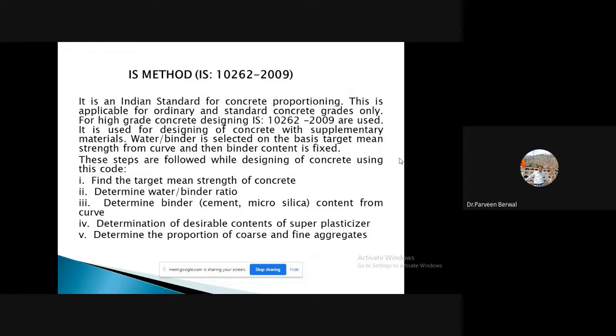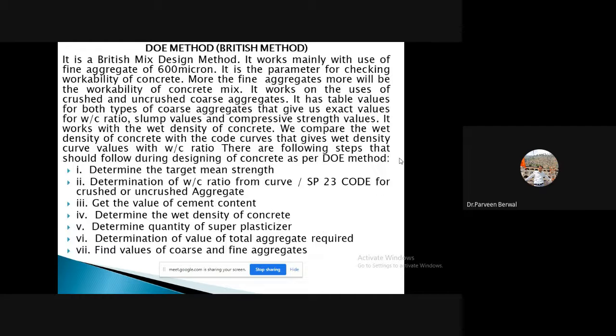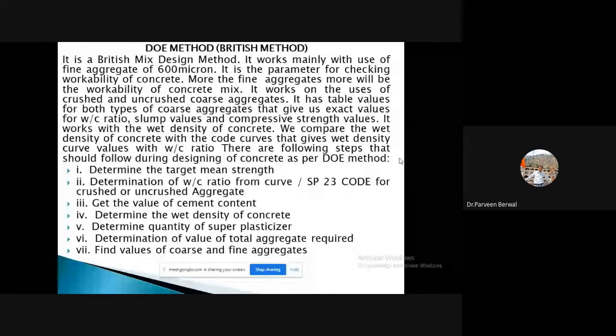It includes basically the following steps: find the target mean strength of the concrete, determine the water binder ratio, and determine the content from the curve for the cement and microsilica, determine the desirable content of the superplasticizer, and determine the proportion of the coarse and fine aggregate. Then we talk about the DOE method, that is basically a British method.